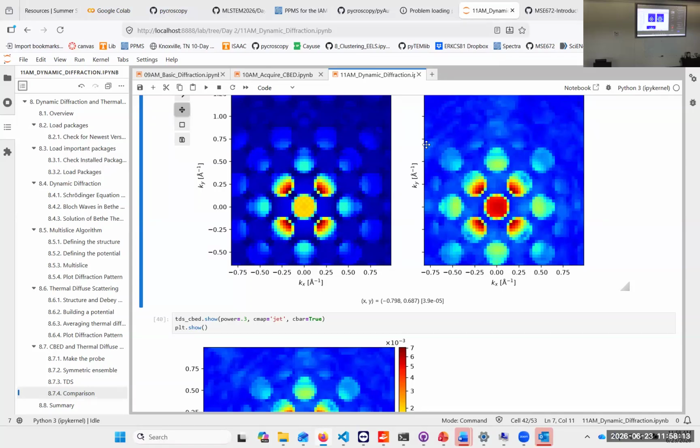Yes, that's exactly the point. The perfect ensemble cannot have Kikuchi lines. It actually has very weak ones, so if you do it much thicker, you'll find a little bit. But the Kikuchi lines really come from an interaction of the electrons with the phonons. So if you don't put them in, you don't get them. You get a weird effect at some point.